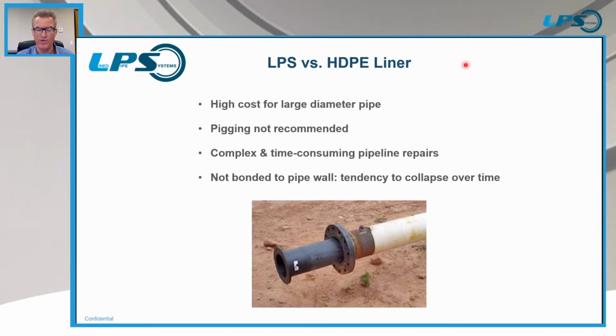Particularly if you want to monitor the pipeline using an intelligent pig, it's really not recommended. They can get stuck because the liner might contract a little off the pipe wall, and again, it just causes undue stress. It's not needed on the liner. Complex and time-consuming pipeline repairs. It's very complicated. What they generally do is they'll build a 500 meter section, pull the liner through that section and flange it on each end. Well, if you have a repair, you can't do much with it.